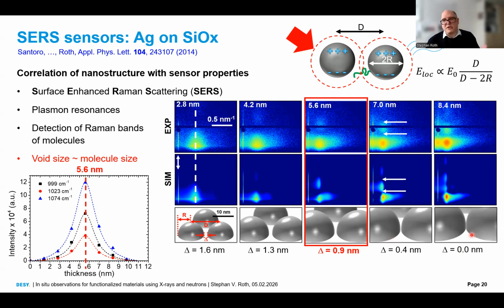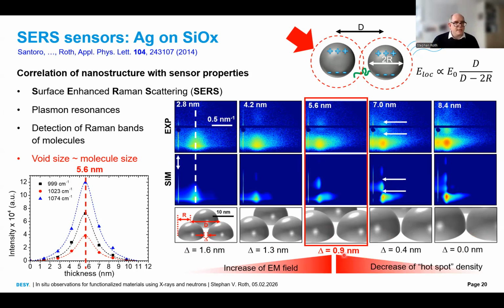When the clusters touch each other, you cannot put a molecule in. It's exactly what you see. First, the cluster surfaces become closer to each other. You have an increase of the electromagnetic field up to 0.9 nanometer, and then again you have a decrease in hotspot density because the clusters grow together. You have an optimum around 0.9 nanometer of void size, and this occurs around 5.6 nanometer, fitting perfectly what you measure here. So this was a very nice example to understand the functionality of the sensor based purely on the structure.